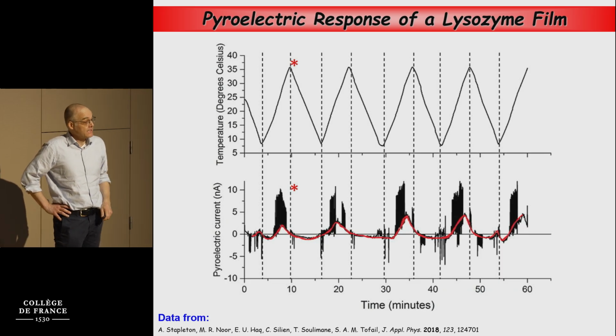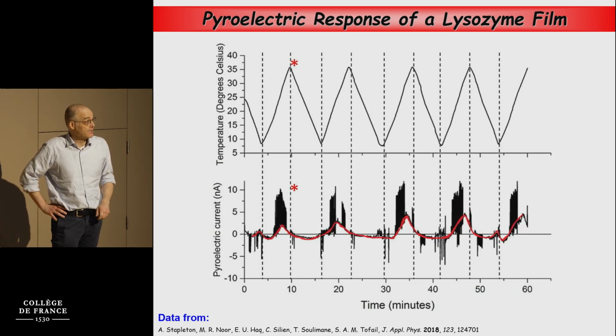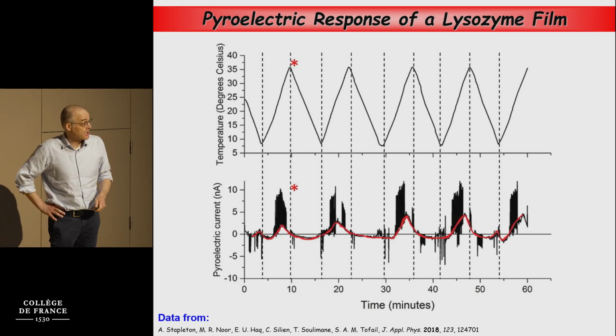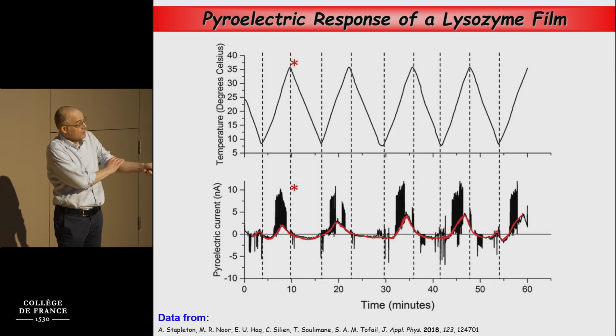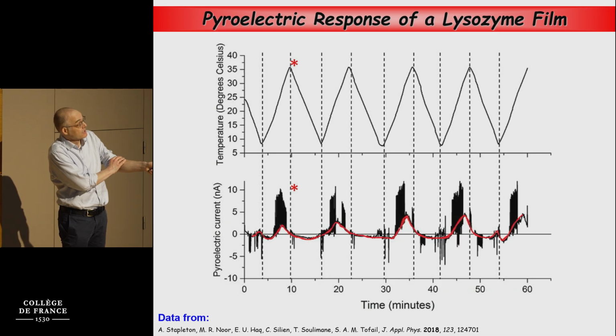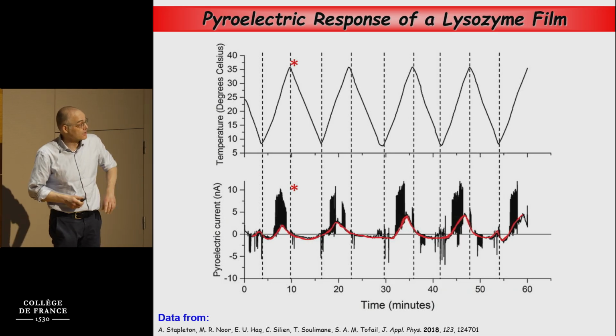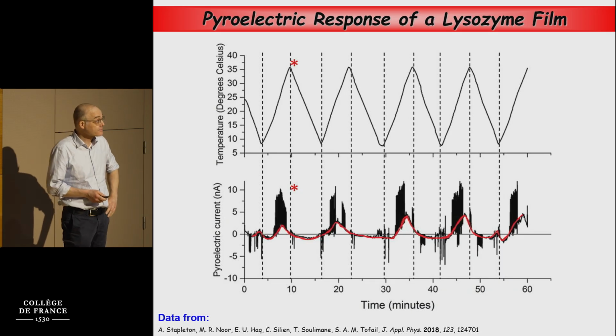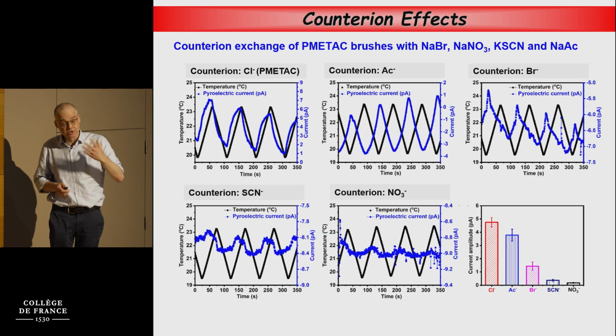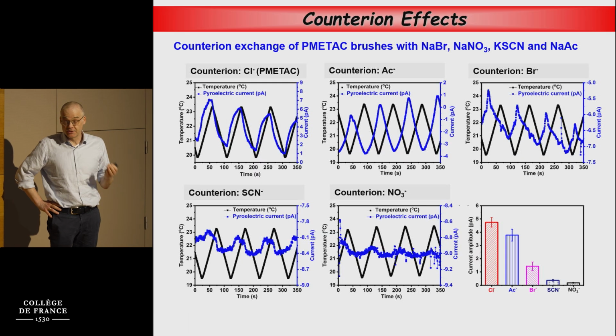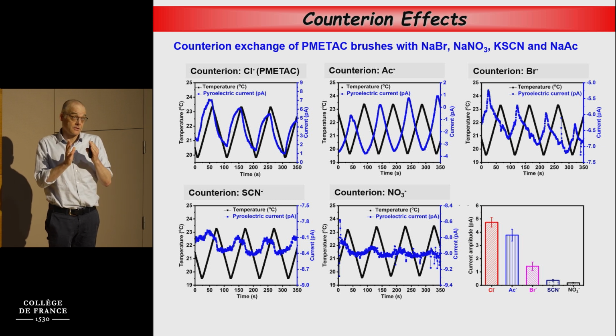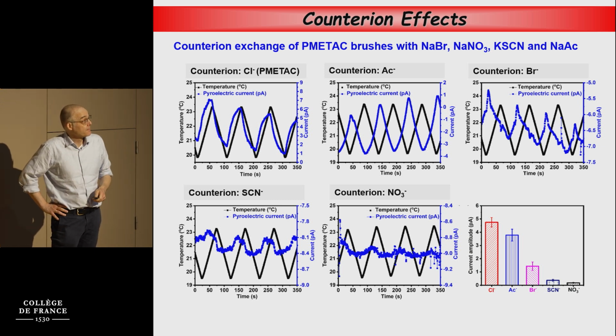The behavior we've seen for these zwitterions and electrolyte films is not unique, however. There are experiments being published where people looked at very thin protein films, so this is L-lysozyme, that also shows the same type of triangular modulation in current as a function of time. And so we think this has to do with the mechanism behind this, which is different from dipoles that are due to crystalline domains.